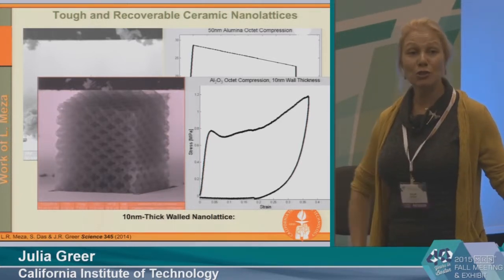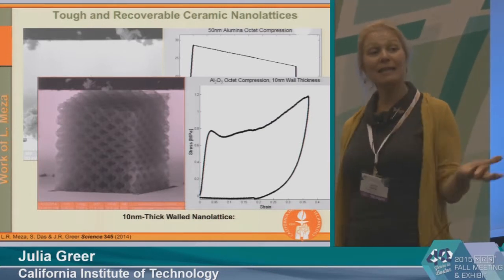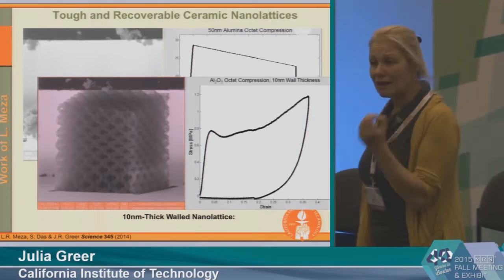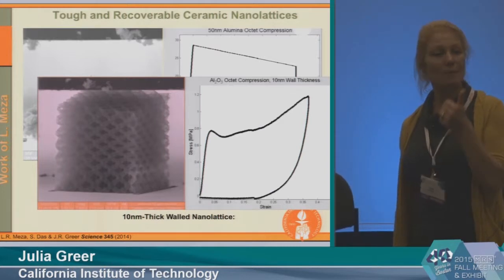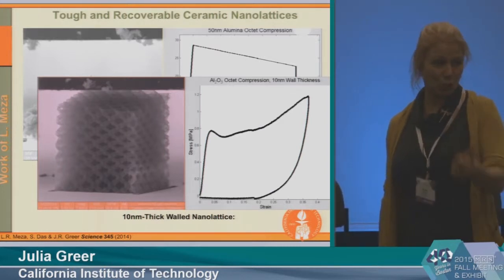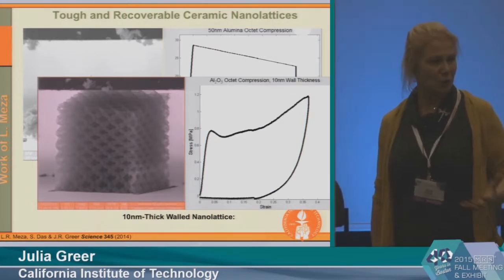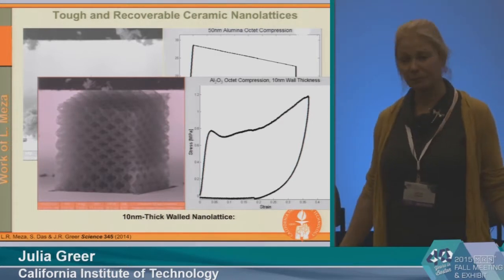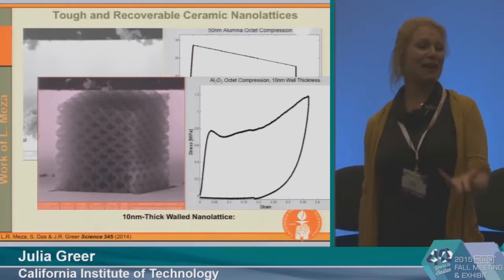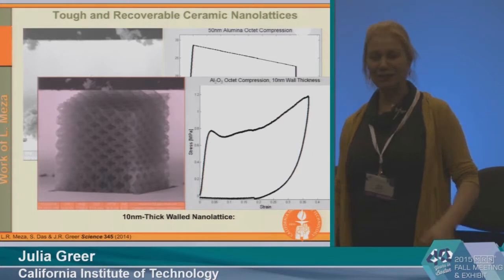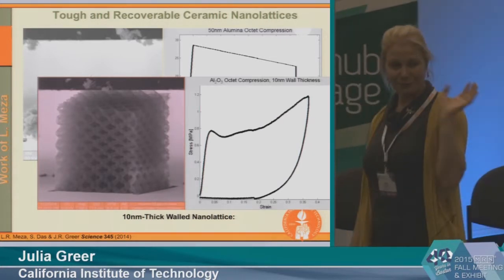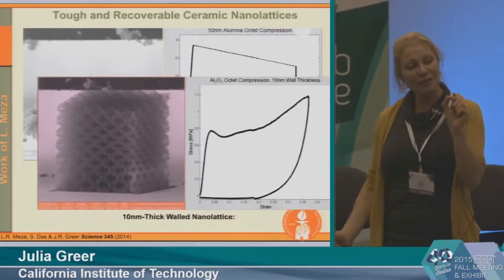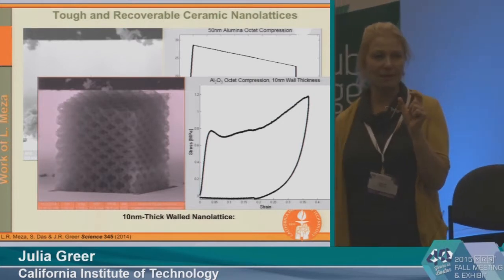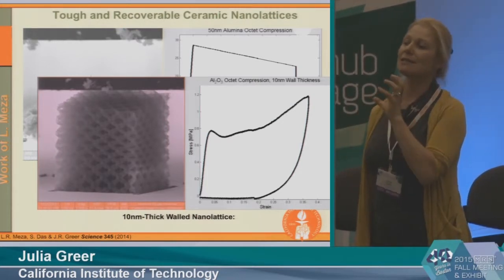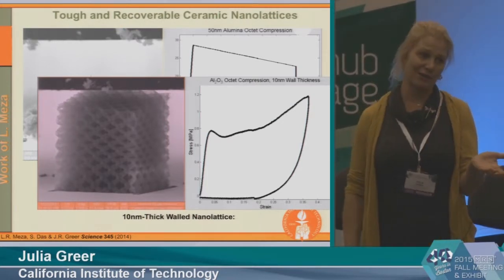So my student Lucas just made a ceramic that's 99.9% air. That's relatively strong. That's completely damage tolerant. You can push on it until you're blue in the face and it'll always recover. Ceramics are not supposed to do that. So if that doesn't teach you that the size effect is real, then this whole point of my talking here is completely lost. So the only difference between these two is the wall thickness. And so what you can see is that you can elicit entirely diametrically opposite behavior out of these.